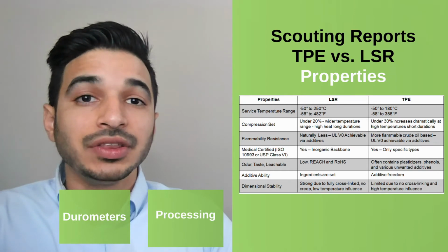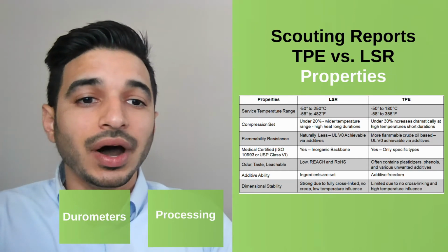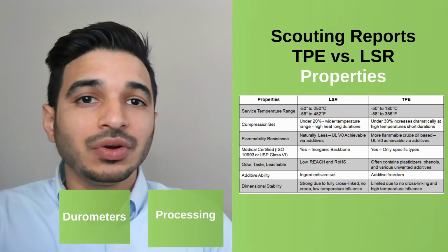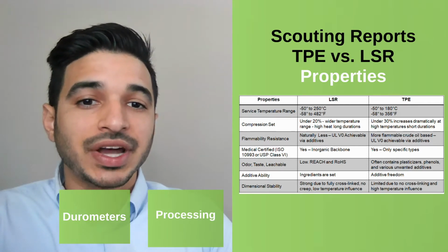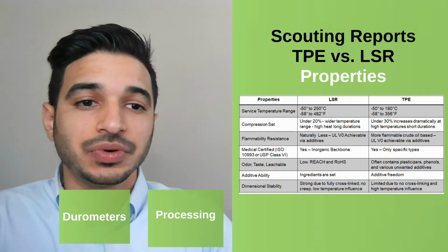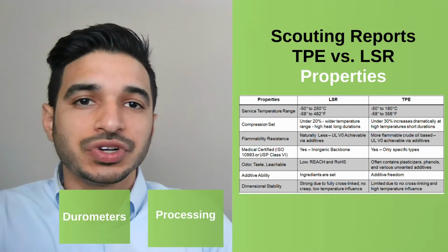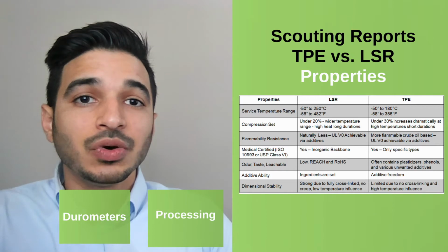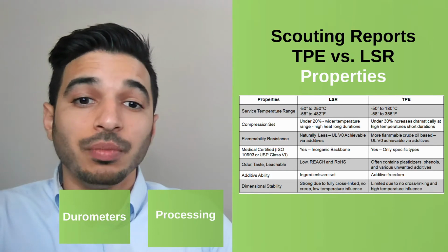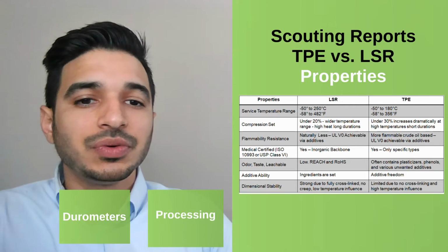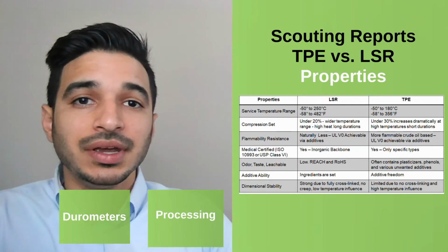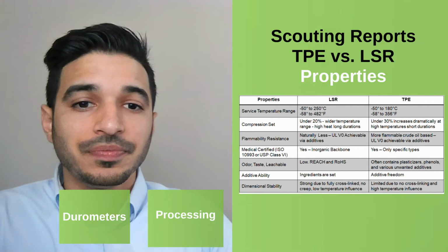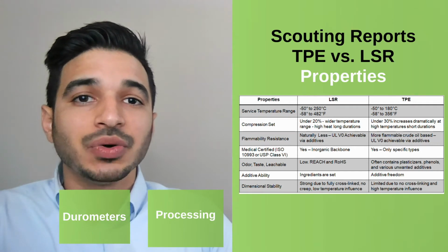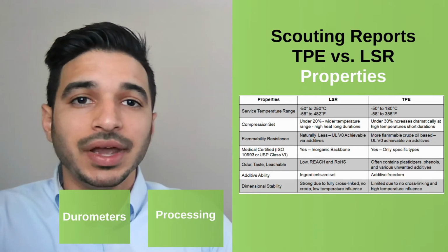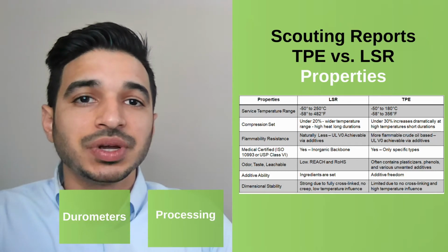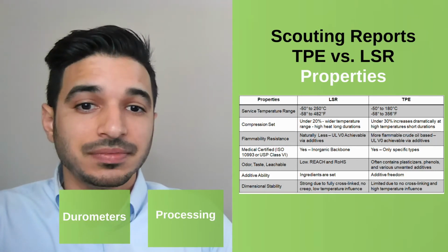For TPE and those specialty grades for TPE, they can go under 30%. And it can only do this for a lower temperature range as we described above in the service temperature range, and only for short durations. Typically, TPE can go even above that to 60% or more. When it comes to flammability resistance, both LSR and TPE are able to achieve UL V0. However, LSR is naturally going to be less flammable because of its chemical makeup, whereas TPE is naturally more flammable as it is crude oil based.